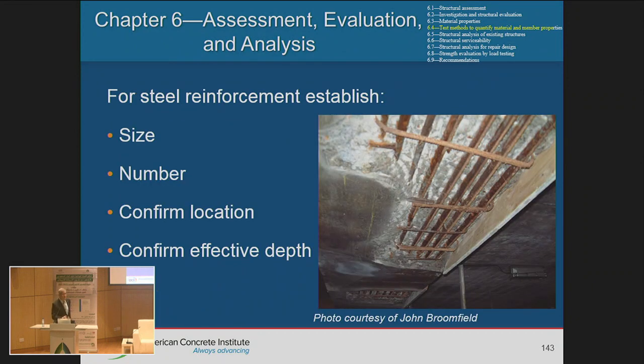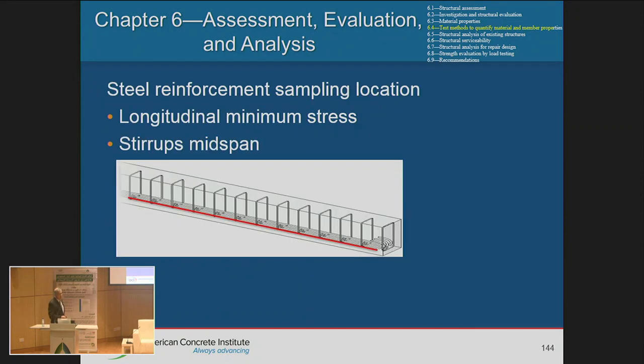For steel, when I check, I need to determine the size, number, confirm location, and effective depth. So when I take my samples, where do I take them from? If I'm looking at flexure, if I'm taking longitudinal bar, where would I take my samples for a simply supported member? You try to take them where you have the minimum strength, right? Which would be closer to the ends. That's where your minimum strength is. And for shear, where you have the minimum shear, which is usually, for uniformly loaded, at midspan.